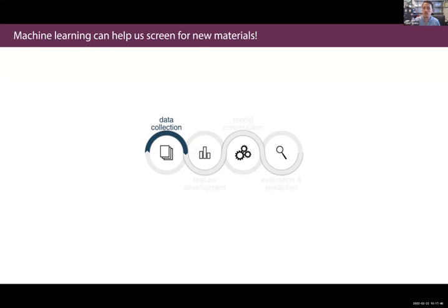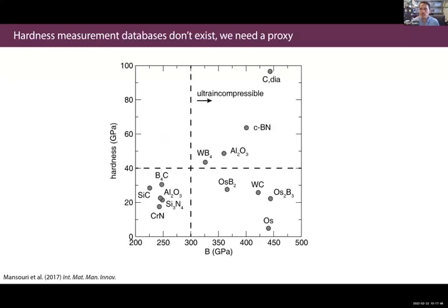That's the general flow. So where's the data going to come from here? And what data is there? Well, the problem with hardness is that there's like 10 different ways to measure it. There's Shore hardness, Knoop, Rockwell, Brinell, on and on. There's all these terrible ways to measure hardness, and they don't even have the same scale that they report the value on. So if you tried to gather data from literature, you're going to run into the problem of highly what we call heterogeneous data. It's all over the place. So that's not a good option.